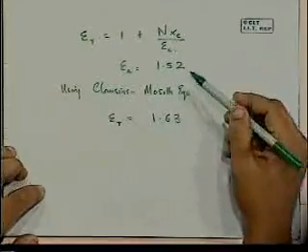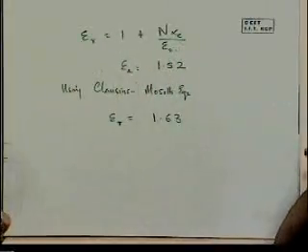So the approximation that we use, namely that the dipoles experience simply the applied field, gives us a lower value for the dielectric constant than what Clausius-Mossotti gives us, namely that now we are taking the individual dipoles experiencing a particular local field that varies from dipole to dipole. So we are underestimating when we make that approximation. And the same kind of approach could be used for other materials to calculate the dielectric constant.